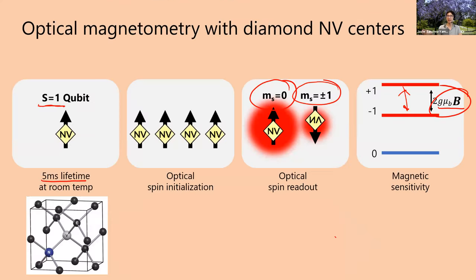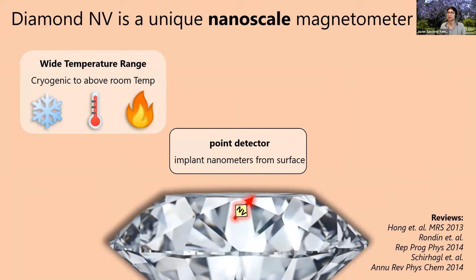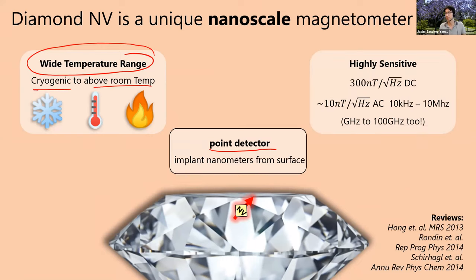All right, so that's how we do NV optical magnetometry. Now, why is it a good nanoscale magnetometer? There are a couple of reasons. One, which is really special and unique to atomic defects, is that as a sensor it's as small as you can make it. It's defined by two atom defects in diamond, so it's only a couple of angstroms in volume. We can also implant it nanometers from the surface of the diamond, so we can bring it really close to some other material of interest. It operates over a very wide temperature range, from cryogenic to above room temperature, and it's also highly sensitive.